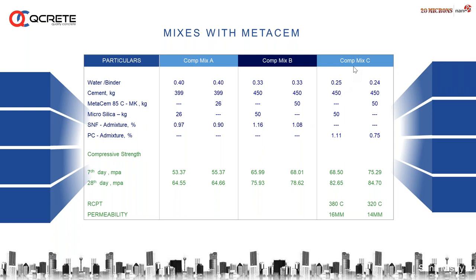The third one is where we conducted a trial, and we evaluated for the RCPT test also, using 50 kg of Metakaolin. We can achieve the strength, yes, the first criteria of 82, 84 is achievable in both the concrete, whereas the Metakaolin is showing 320 coulombs and the permeability is 14 mm, and strength part is also, see comparatively, a little bit on a higher side compared to the analog mineral admixtures, and on a 7 day strength it is further higher by almost 5 to 6 MPa. So these are the mix comparisons between the analog mineral admixtures available in the market.